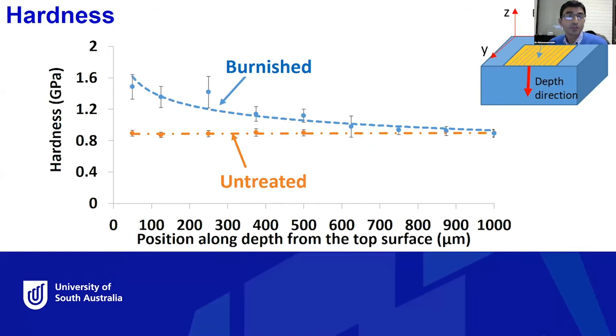In order to confirm the surface integrity, and how the burnishing has also improved the mechanical property, which is the hardness, we measured the nano hardness by nano indenter on the burnished surface and also the untreated surface. Because burnishing is a mechanical cold working process, we expect a microstructural change and deformation of the grain, and some sort of hardness improvement. We can see that burnishing actually improved the hardness at the top surface, right here.